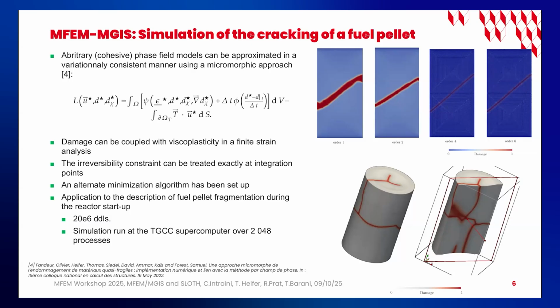And at the end, this creates elastic stresses inside the pellets, which are relieved by the creation of these crack networks that you can see here in red. This is the simulated one. And this is the kind of simulation that we were able to do with MFEM-MGIS with about 20 million degrees of freedom. And this shows the coupling between heat transfer analysis, the micromorphic approach to damage, and mechanics. The simulations were run on our French supercomputer TGCC on about 2,000 MPI processes with good scalability. So at the end, you see this complex crack propagation.